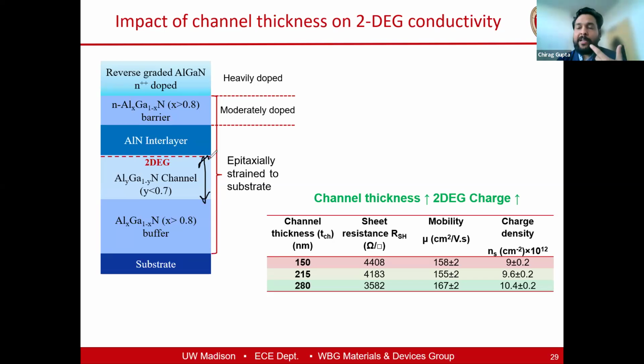However, you also want your channel to grow pseudomorphically on the substrate. And since there is some lattice mismatch between the channel, which is less than 70% AlGaN, versus aluminum nitride, there is a certain limit to which you can deposit the channel thickness. And this is what we were able to do. We were able to deposit 280 nanometers of channel without introducing too many new defects, with optimizations, and we got somewhere close to 3600 ohm per square as the sheet resistance.